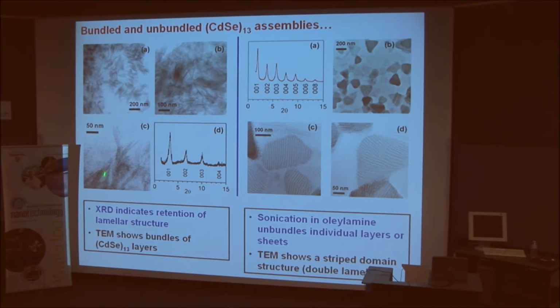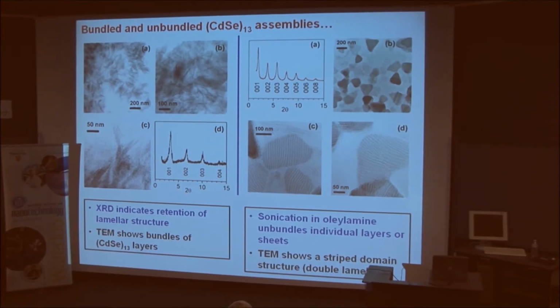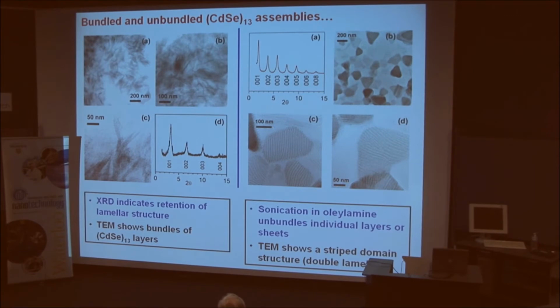And if you look at them, you can see that they have lamellar structures. These wispy bundles actually consist of layers, just as I suggested on the previous slide. And in fact, we still get low-angle diffraction. So these have CdSe 13 clusters entrained within the templates, which still have a lamellar structure.